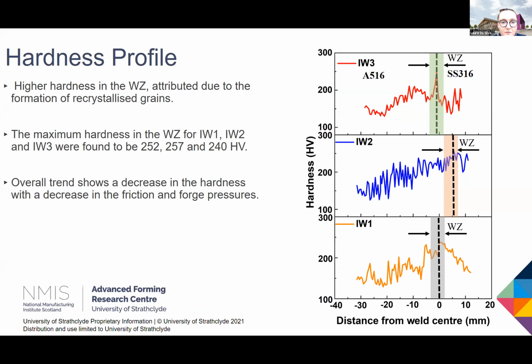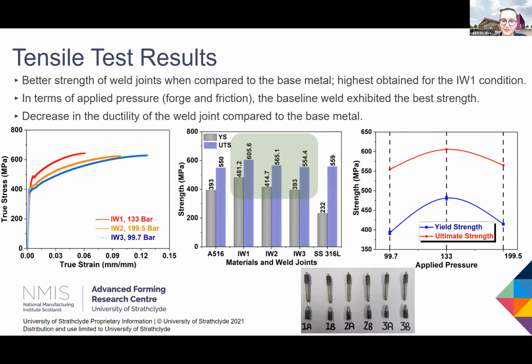Looking at the hardness profile, we can see that there's a slightly higher peak in hardness in the weld zone due to the finer recrystallized grains, as we would expect, but there's not that much difference in the maximum hardness. For all welds, the range is from about 240 to 257 Vickers. And the overall trend shows a decrease in hardness with a decrease in the friction and forge pressure, as you would expect. Moving on to the tensile test results, our little figure at the bottom shows that all tests failed at the same area, and it was actually within the base material of the A516 ferritic steel, which is what we would like.